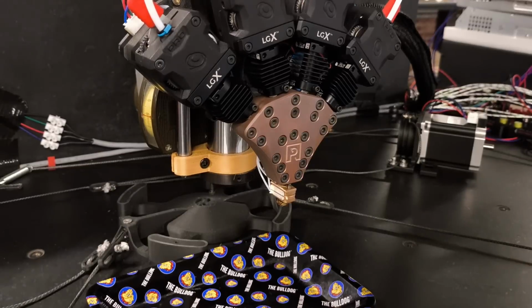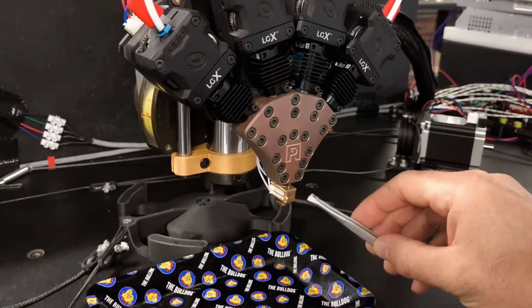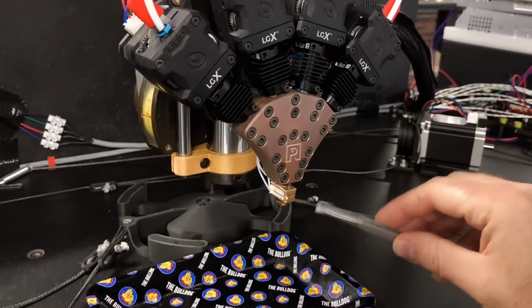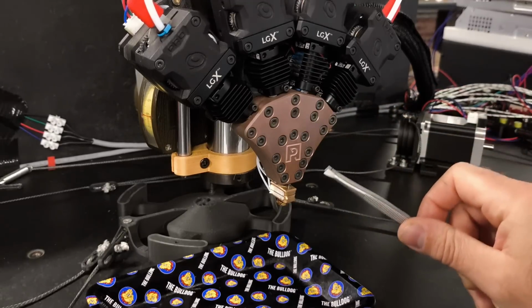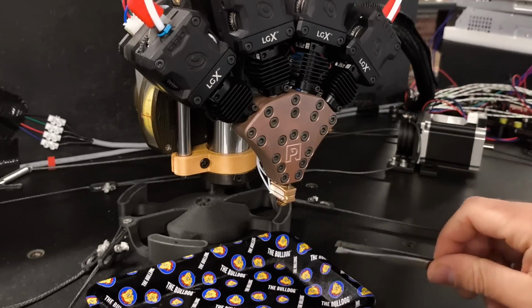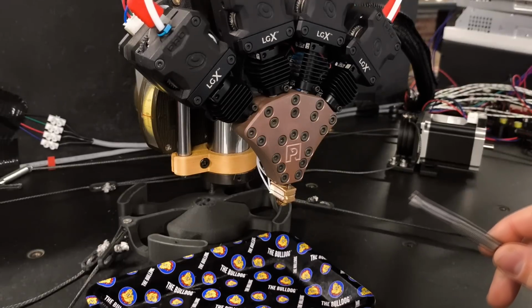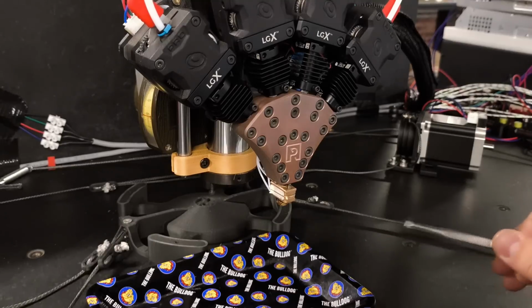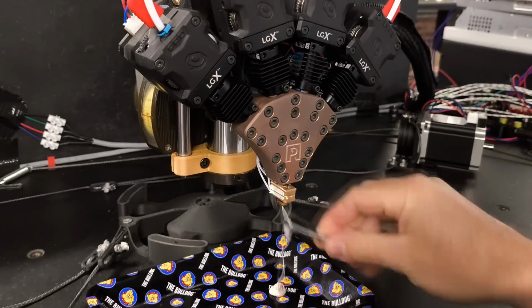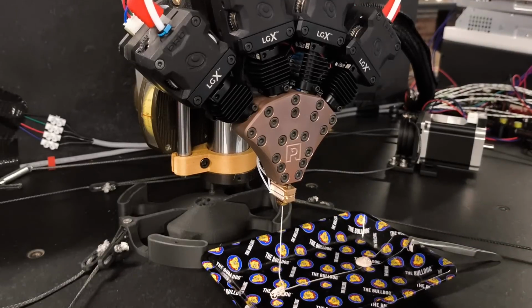We heat it up. This is at 270, this is at 240. We're gonna extrude a purge to flush all the pre-melted filament out of there. And then we're going with 10 grams of filament that should be on the tray later on. This will take approximately 27 seconds. This is at 300 cubic millimeters a second. All right, so go.